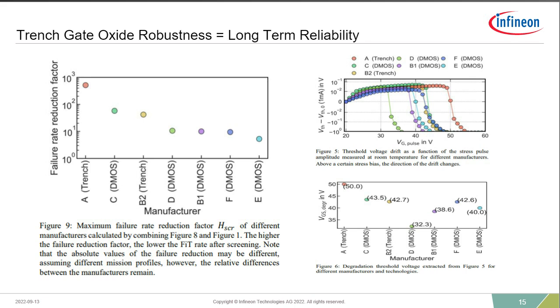And when you compare that to the long-term reliability of the devices, what you see here is that Infineon devices generally have essentially an order of magnitude higher reliability than some other devices on the marketplace. And this is primarily driven by the thickness of our gate oxide structure and the trench-based topology of our devices. So this is just a comparison between devices. You can do this in your own lab and compare other devices. We do have a white paper on our website about this, and of course you can also look up the Ohio State paper that's been done on this as well.